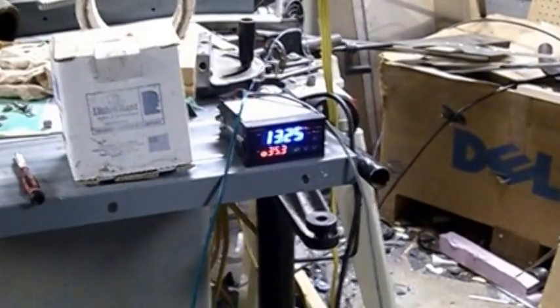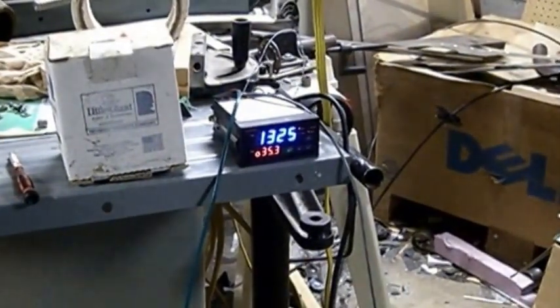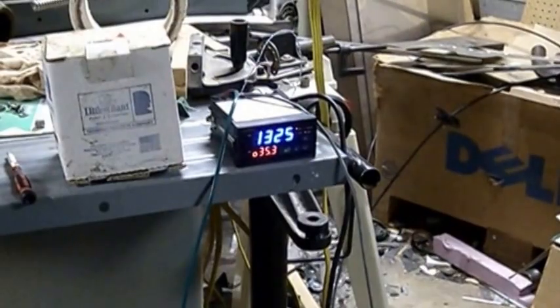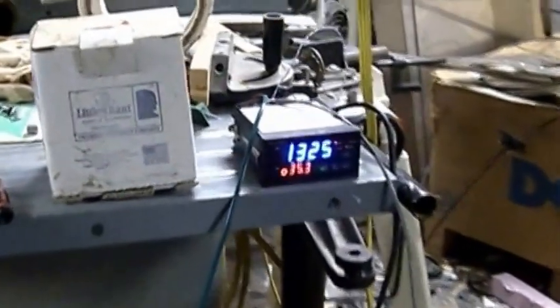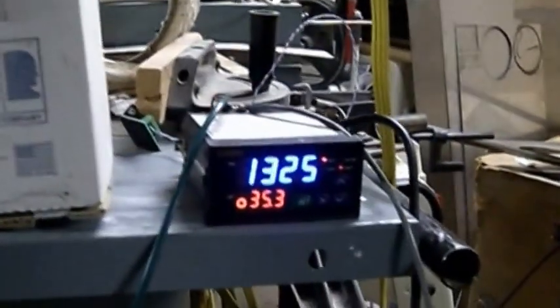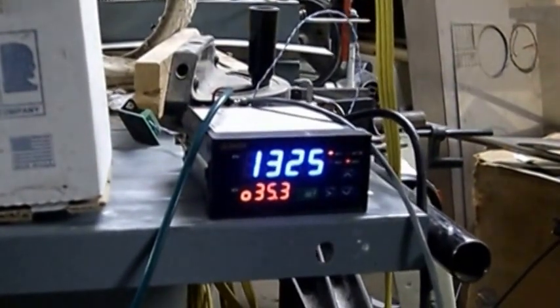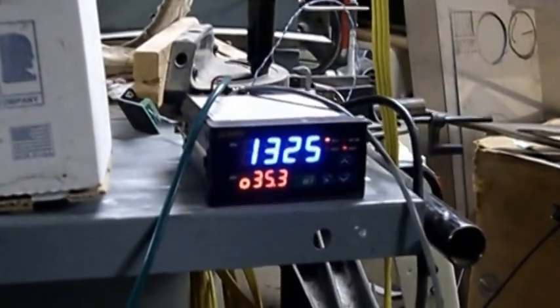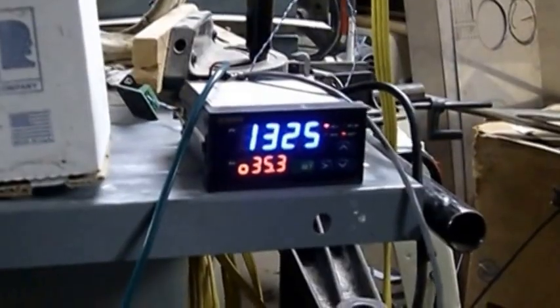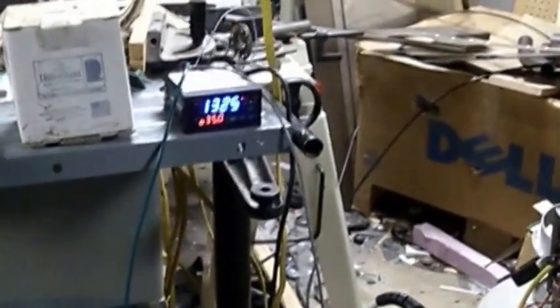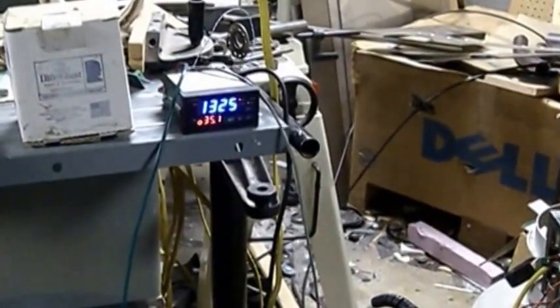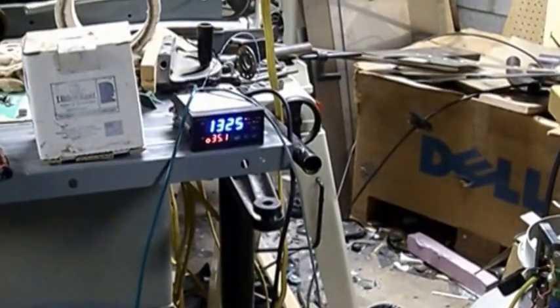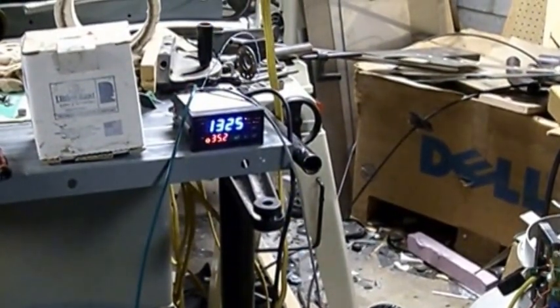Alright, here we are. We finally got to the holding temperature, 1325. It's holding pretty good. What you can see is that the gas valve is at 35.3, which is about the same as it was at 1050 without the heat exchanger. So a huge improvement in the efficiency, especially at these ridiculous temperatures above cone 10. So we're in the hold. Let's take a look at the kiln.